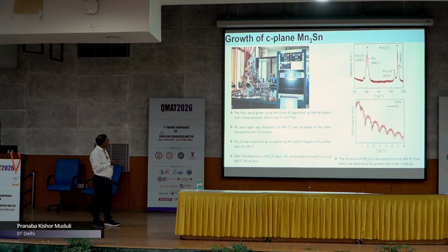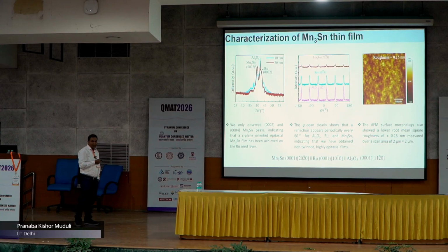So, we grow these Mn3Sn films using ruthenium as a seed layer on the sapphire substrate. So, we have a C-plane sapphire, on that we use a ruthenium seed, and then we are able to grow Mn3Sn, and these are epitaxial films. This is X-ray reflectivity showing a lot of nice fringes indicating the quality of the film is good. We also check the fact that it's actually epitaxial by doing this so-called phi scan, and you can see that we see these 6 peaks indicating the hexagonal symmetry, and that matches with the substrate and seed and the Mn3Sn, indicating we have good epitaxial film, and this is the relation. Also, the roughness is quite low.